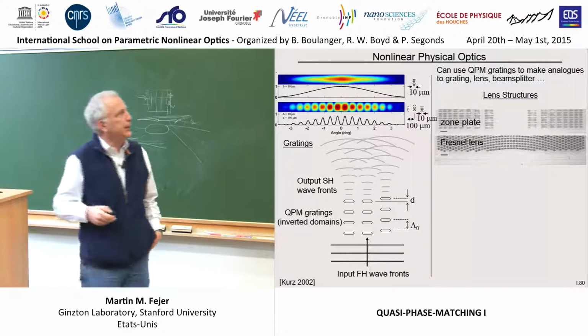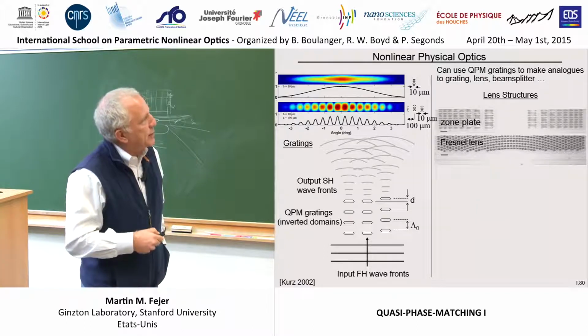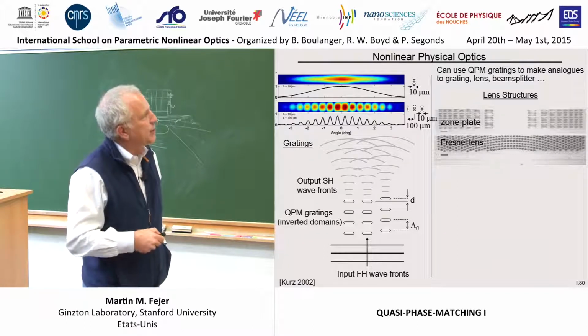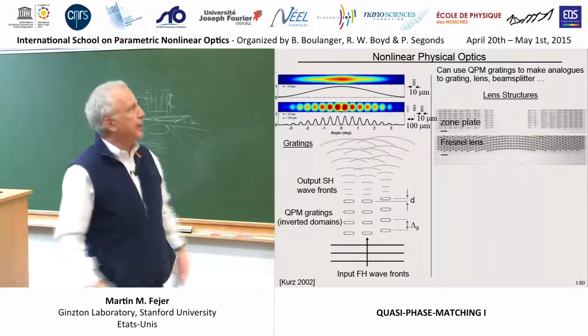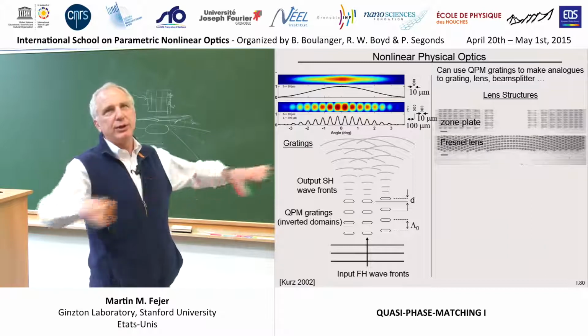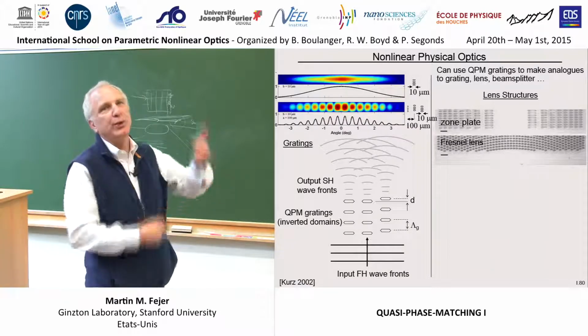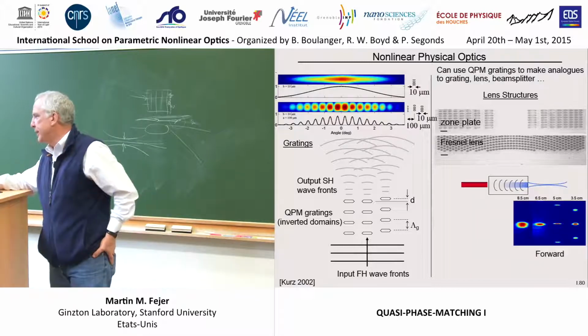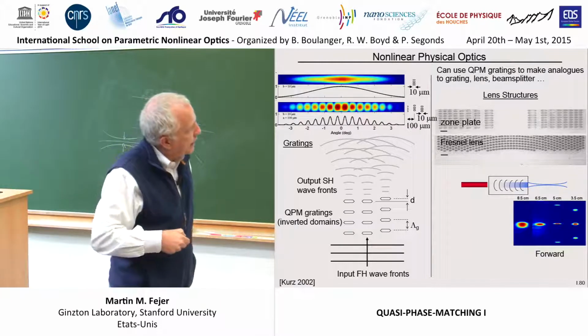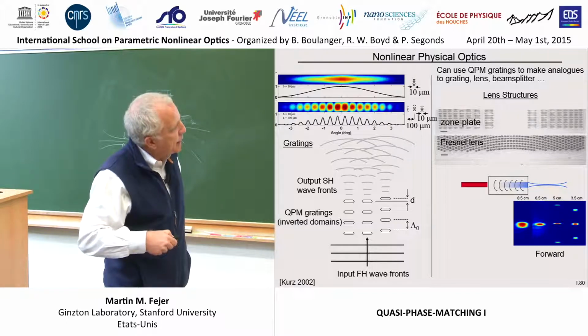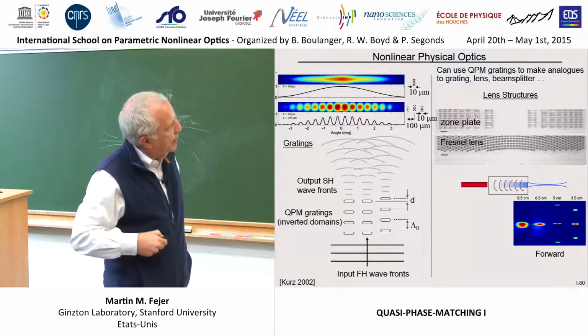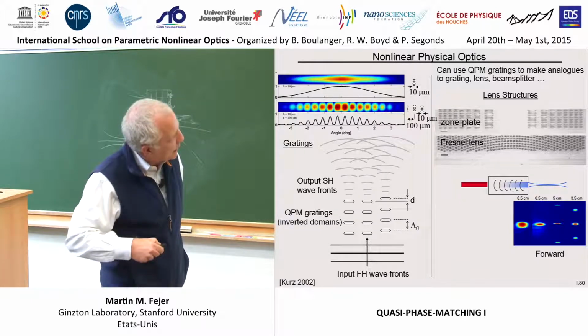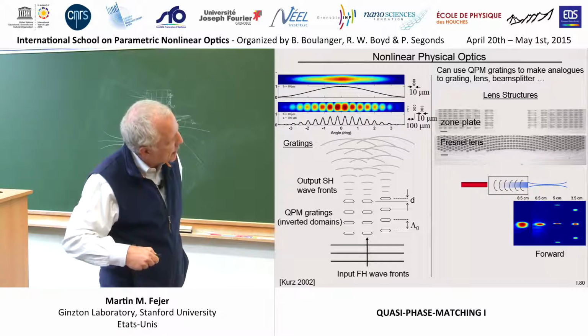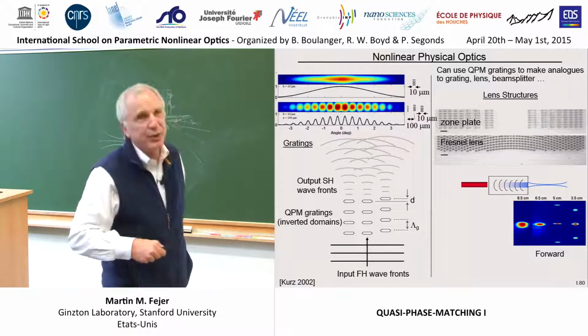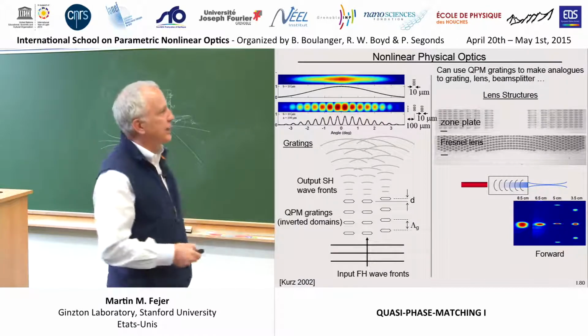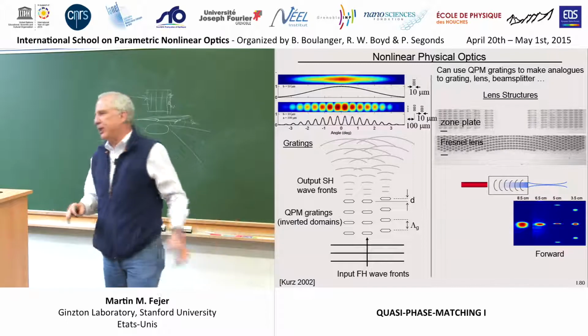Perhaps more neat is, what if you arrange these things as a Fresnel zone plate or as a Fresnel lens, which is, again, something well known in linear optics, but here these are, again, uniform structures in the linear sense, but their nonlinear behavior has been transversely patterned. And if you put one of these things in a Gaussian beam, say the Fresnel lens here, with the curvature oriented this way, it makes a focused beam. And if you take a look at various slices after the crystal, you see it's getting smaller and smaller, comes to a focus, and then starts to spread out again, just like a lens would have done. But again, this was just second harmonic generation with no linear property variations.